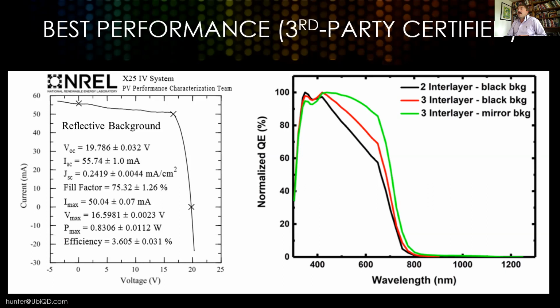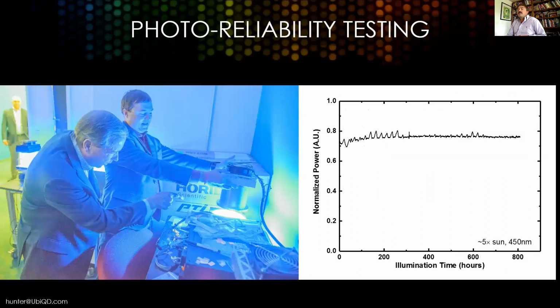And then you can see on the right that part of the way we got there was by adding absorption, by adding these additional interlayers. And that gives you more full absorption in the spectrum. And so that gives you more current, essentially, in the final device. Of course, it's not going to be very useful if these degrade quickly in the sun. And so it's something we've worked a lot on.